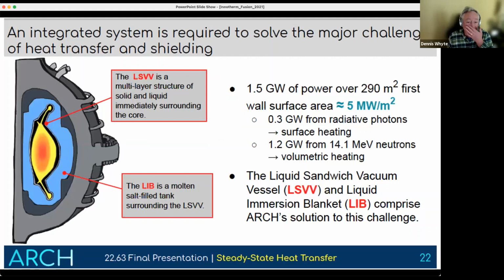So we came up with two kinds of different innovations within this. We redesigned the first wall. We redesigned the vacuum vessel, and we particularly used something called the LSVV, the liquid sandwich vacuum vessel. I'll show you that. And then we were using the liquid immersion blanket, which was still used pretty much intact from the previous design that I showed you. And we indicated that, in fact, we could reach the thermal heat removal of this, even though now we were pushing the global average up to like 5 megawatts per square meter, which is really pushing the frontiers. Yet we could even use more, in fact, if we came up with it.